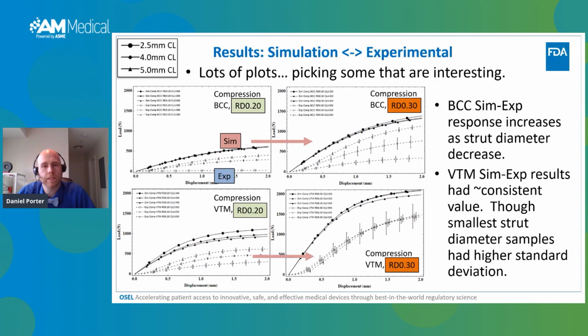And the general conclusions are that the difference in simulation and experimental, or the kind of error you get, seems to increase as the strut diameter decreases. The Voronoi generally showed this same trend in compression, except when we got into potential powder removal issues.